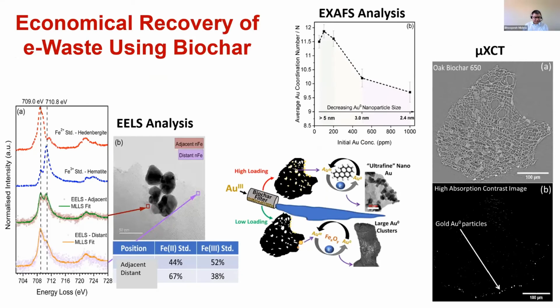We also did some EELS analysis to show that the position adjacent to these gold clusters had a higher percent of iron 3, and distant from these, it was higher iron 2. So nearby was more iron 3, and farther away was more iron 2. This was a smoking gun, proof that these iron oxides are responsible for the reduction of gold 3 into gold 0. And XAFS also shows that as we go to higher loading, the particle size decreases.